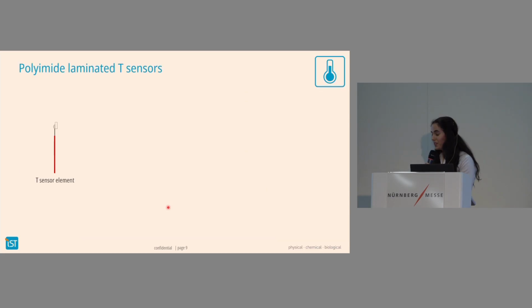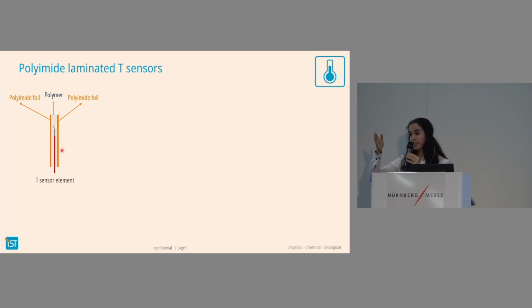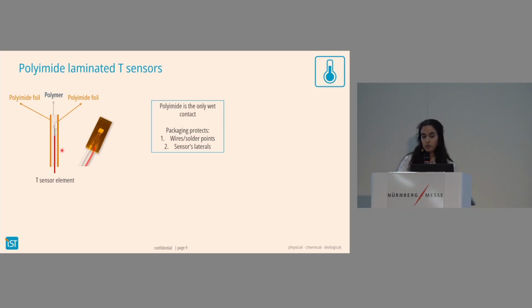Now, another question that we also normally have is that the sensor may not come in contact with the media or vice versa. So for that, we have developed this technique for packing the sensor in a polyimide layer. So we start with the temperature sensor element, and we do like a sandwich where we have polymers left and right. And to stick these two together, we put a polymer in the middle. The key here is to make this in a way that it's as small as possible and as thin as possible so that we don't have a lot of extra material that comes in contact with the medium. This is how the sensor looks like. And what is special then is that this packaging protects these wires and these soldering contacts, as well as the sensor laterals.